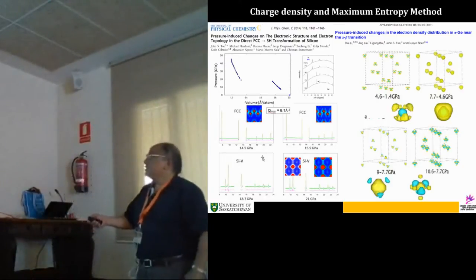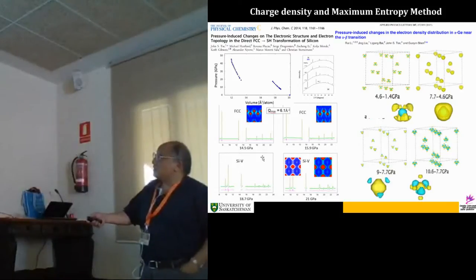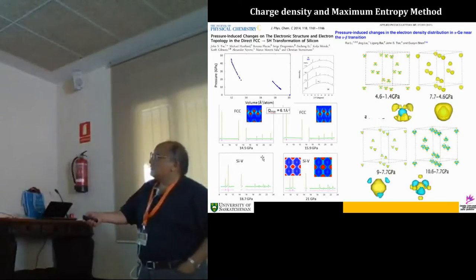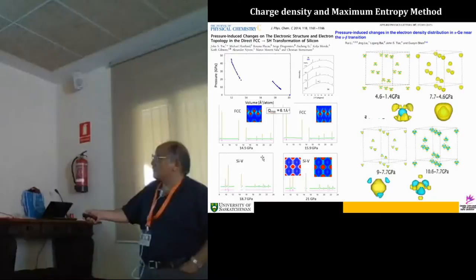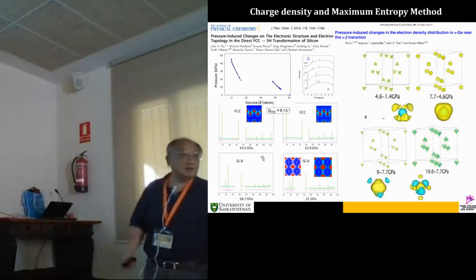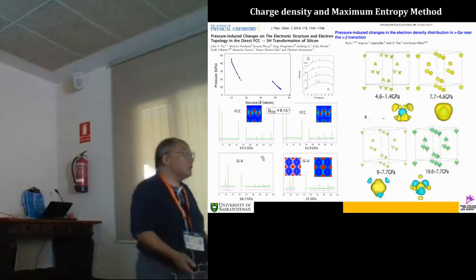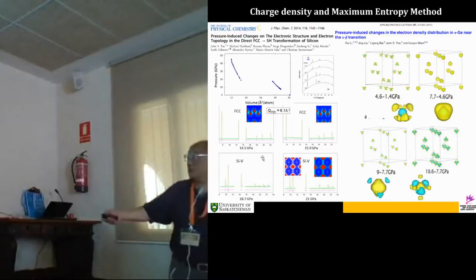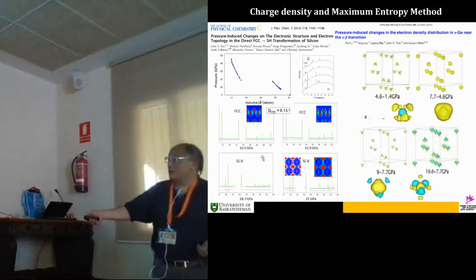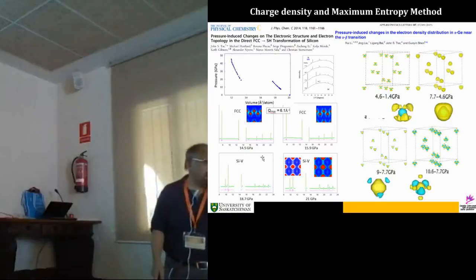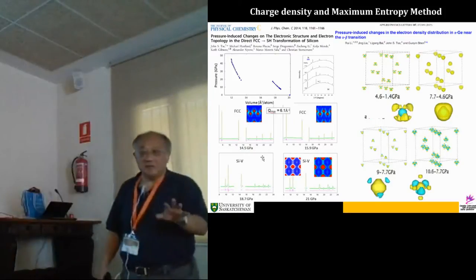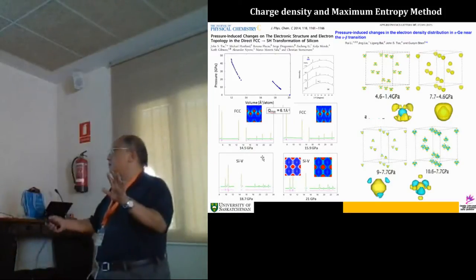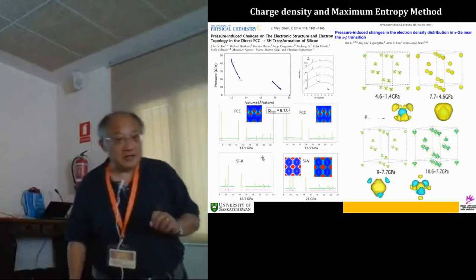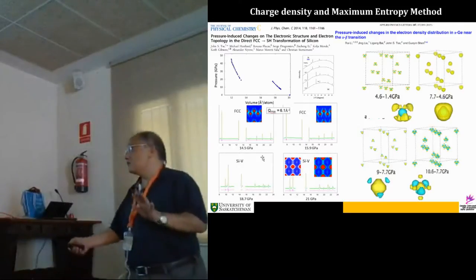All right? So I take that and compress it. You can see the electron density at low pressure, at 14 GPa, and at 15, 16 GPa before transition. You can see the electron already spread out. The reason it spread out is because it involved the d orbitals. And eventually it goes to the hexagonal phase, and this is a calculation, they're almost identical. All right? So the method by itself is approximate, and maximum entropy, a lot of people do not believe it, but to a certain extent it's quite useful.